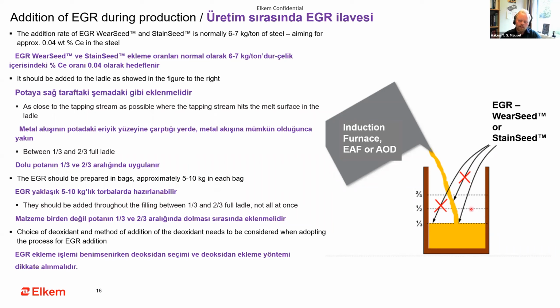So, and if you are really good at how you're doing this, you can obtain up to 70% recovery of the cerium. But one important thing to look through before doing any trials, and that should be discussed with us, is of course the deoxidation practice that the foundry has, because the choice of the deoxidant and the method of addition of the deoxidant needs to be considered before you start using EGR. So if you're adding, for example, aluminium or calcium silicon into the ladle, there needs to be discussions on how to do that properly before we start to add EGR.